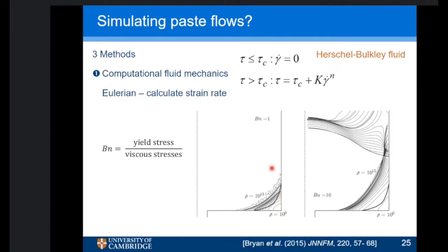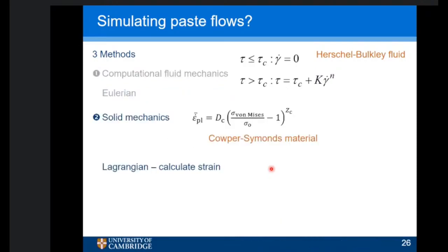Now, there are other ways of doing this, particularly using augmented Lagrangian Eulerian methods in viscoplastic fluids. And they work quite well for 1D and 2D systems. But for 3D systems, they're a real challenge. And for 3D systems with pressure-dependent slip, well, Matt didn't get it to work. So we move on to the other method, or one of the other methods, which is to use solid mechanics approaches. And this is what Harry Ayton, who just finished his PhD, was working on. And he was getting these pressure-dependent wall slip functions to go along there. And there you might work with a thing such as a Cowper-Symonds material, which relates the local plastic strain rate.